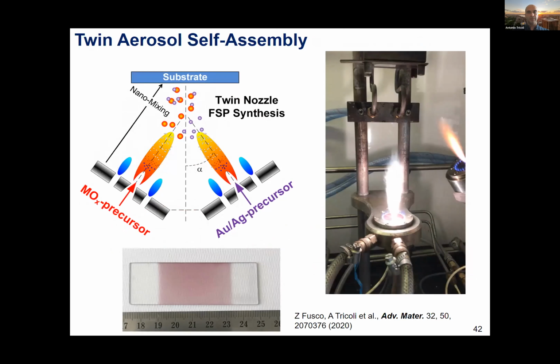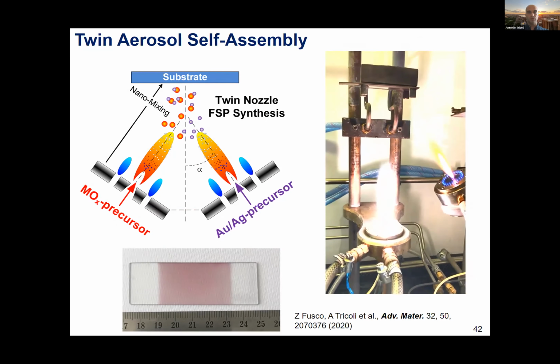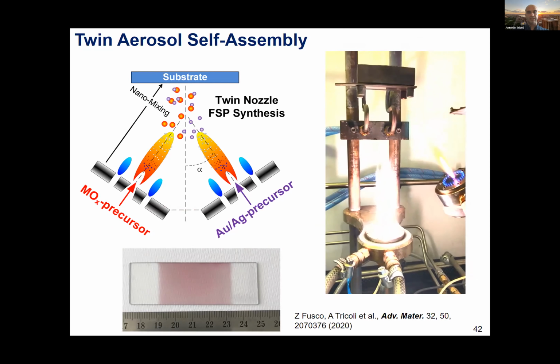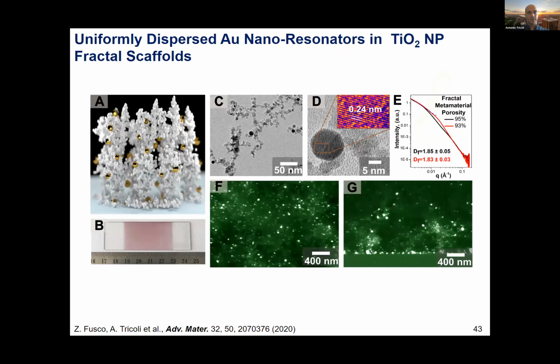This is, instead of using one flame, to use two flames. One flame could produce, for example, as you can see here, one oxide. In this case, we're producing titanium oxide, but it can be bismuth oxide or silica. And the other flame can produce another material. In this case, we're using gold, but it could be another transition metal or semiconductor. Now, when this happens, you produce an aerosol of mixed nanoparticles, which also assemble by the same principle, and are able to make a very uniform surface. In this representation from my student, you can see we imagine, in this case, gold nanoparticles distributed on a fractal matrix of the metal oxide semiconductors. If we characterize this by TEM, we are able indeed to determine the metal oxide and determine the presence of the noble metal, in this case, gold, but it could be another one.